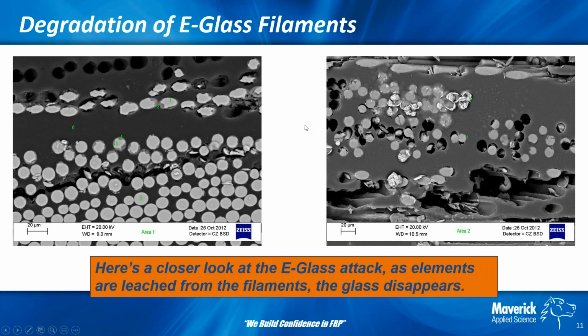Here's another close-up. And you can see very clearly here the voids where the glass is totally gone, and then below that you can start to see individual glass filaments where you see the dark gray around the edges here. So this is basically where the glass is beginning to be attacked. The white is more or less fresh, pristine glass, not fresh, but unaffected, we'll say. And then these dark areas that you see are where the glass is beginning to degrade.